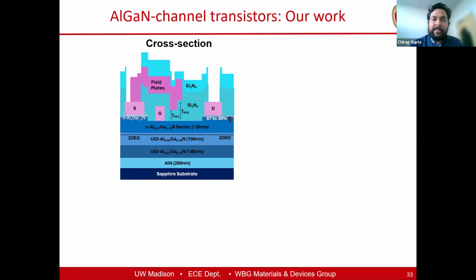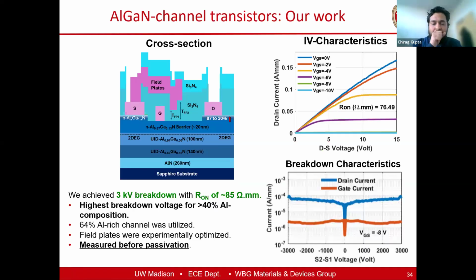We used what is called a reverse grade layer, going from 87% barrier to 30%. We etched it down. We made this design, which is very similar to what you are familiar with in GaN transistors. And what we were able to achieve was 3 kilovolt breakdown with 64% AlGaN channel transistors, and we got around 80 ohm millimeters. So the on resistance is a bit high if you are used to seeing on resistance for gallium nitride transistors.